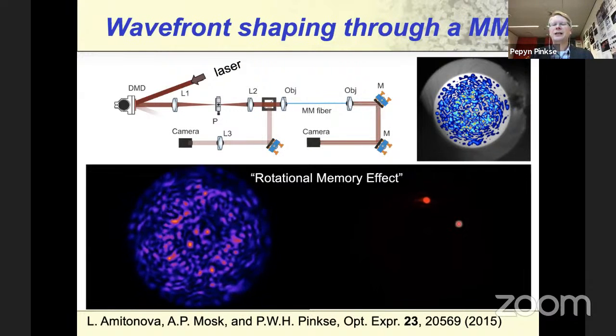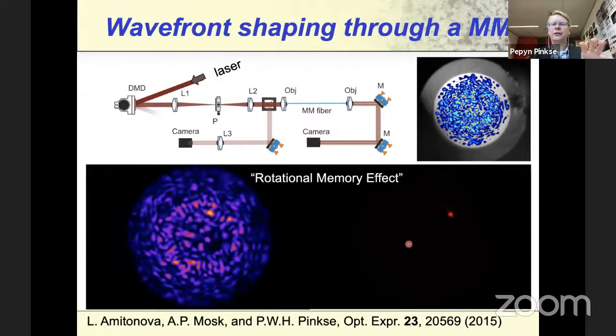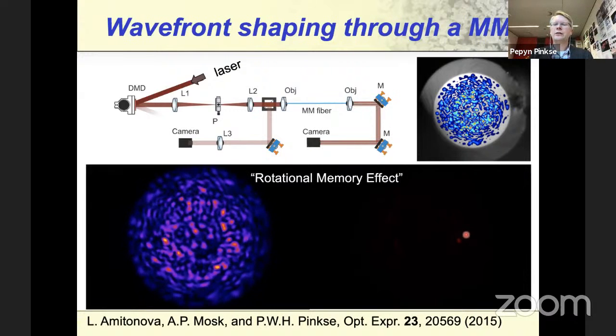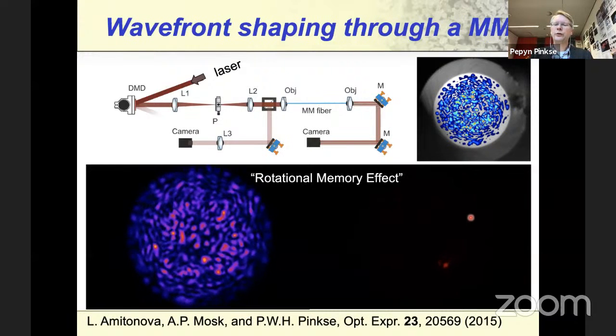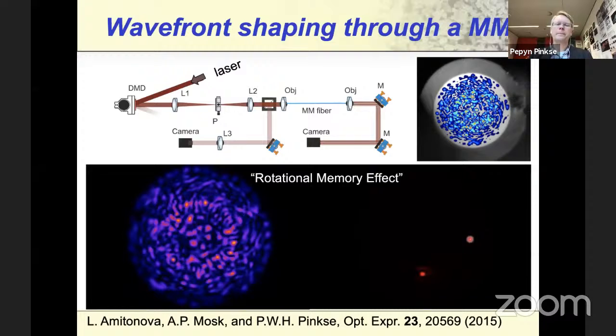And beautifully, we can see now that if you rotate the speckle pattern at the input, to a first degree approximation, what happens is that you still get a focus at the output, but now it's rotated in the same way. I mean, it came as a surprise for us. But if you think about it a little bit more, then it's obvious that this should be the case because optical orbital momentum is to a large degree conserved in these multimode fibers. And this is not only a peculiarity, but you can actually use this for faster scanning of a dot at the output of a fiber, for raster scanning and for imaging.